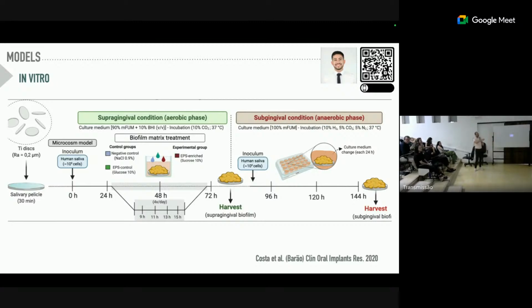So just to show you here, I think I'm out of time. We have been using this in vitro model quite a lot, to have a biofilm that can resemble the composition of peri-implantitis. We also ran some experiments comparing this biofilm with clinical data from studies that collected the biofilm from the peri-implantitis area, and the composition is pretty similar. In this model, we run up to 144 hours. It's not just 2, 3, 24 hours, it's several days.